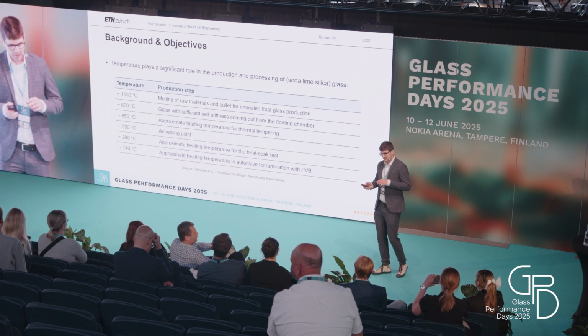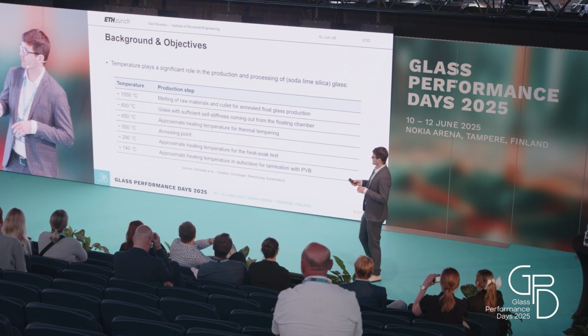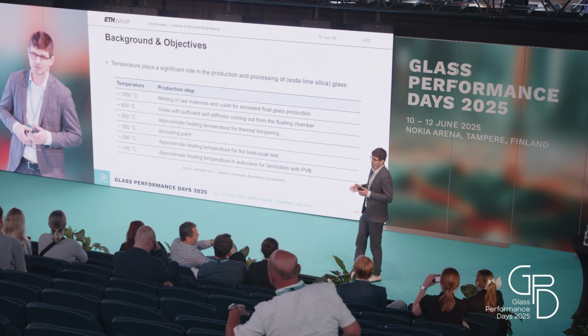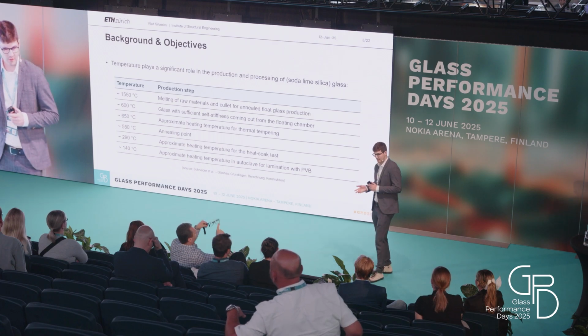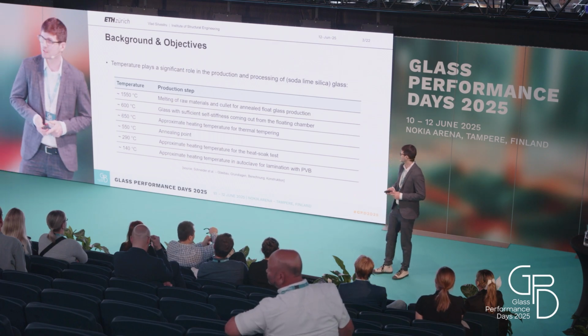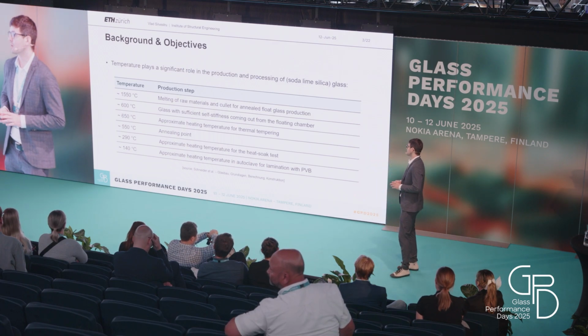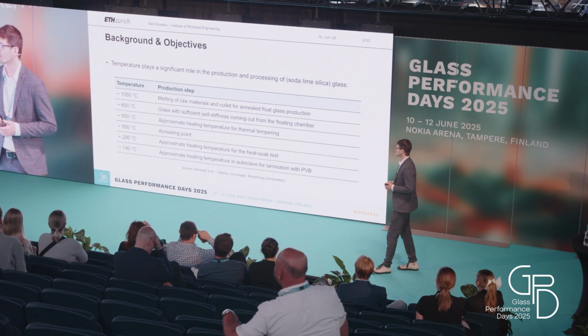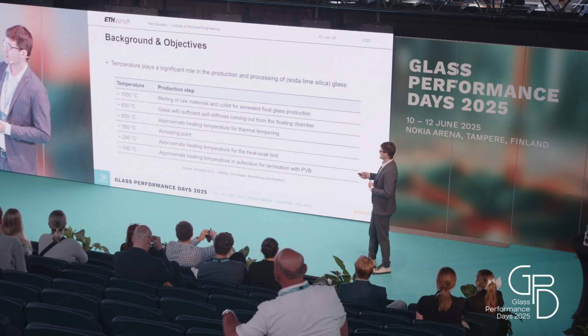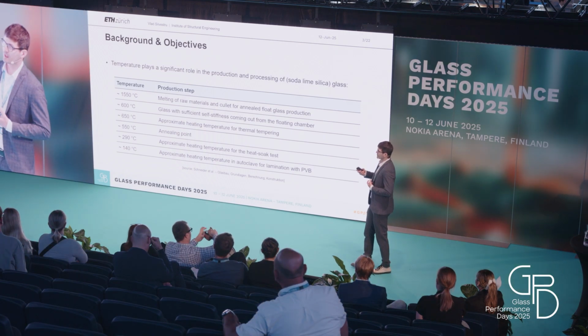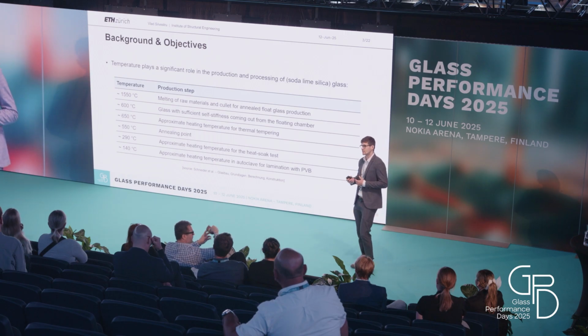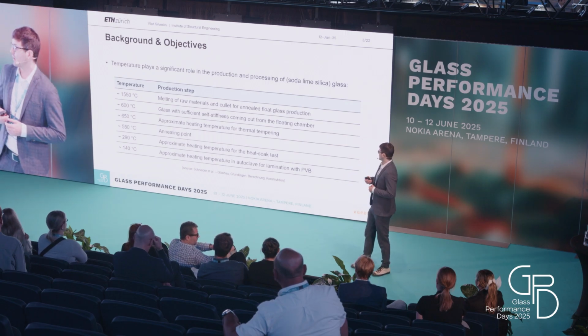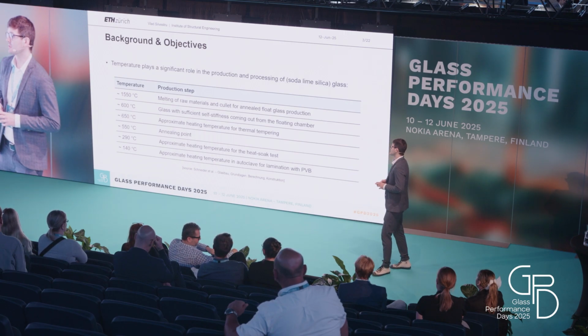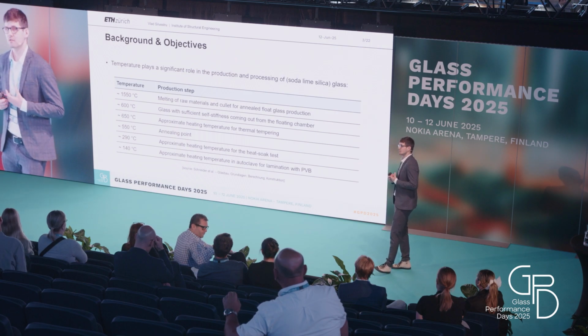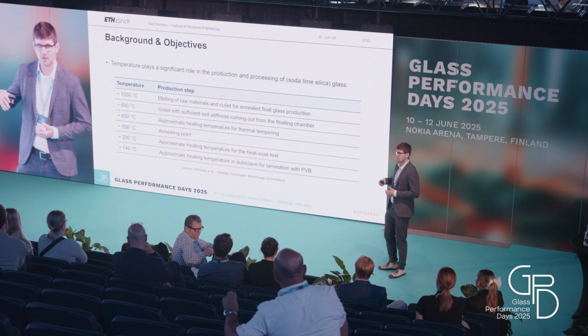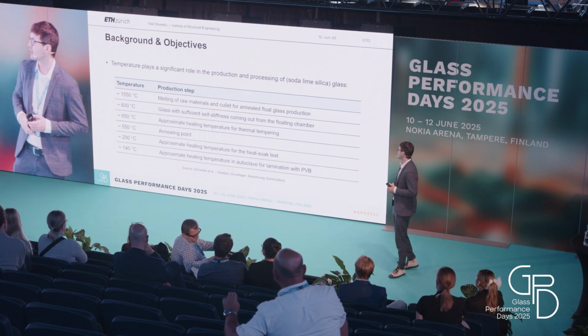I would like to start with this slide showing different temperatures that are used in the production and processing of flat glass. Most of you are probably aware of these temperatures. For me, it was relevant to see what temperatures make sense for the heat treatment that I apply. I would like to point out the 600 degrees at which the glass has sufficient self-stiffness when it comes out from the floating bath.